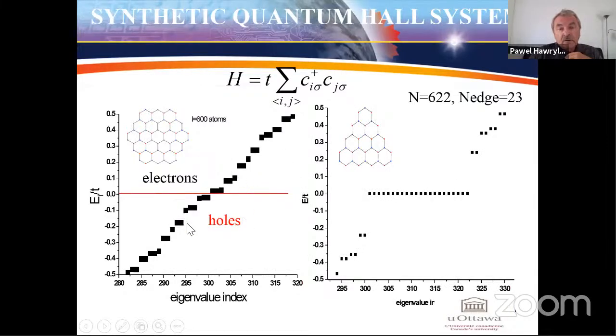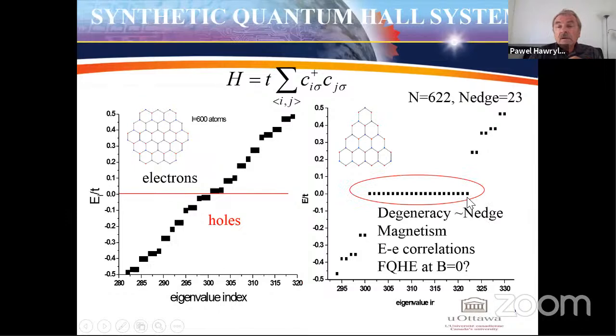Energy levels close to the Fermi level collapse to a degenerate shell. And this degeneracy of the shell is proportional to the number of atoms at the edge. And such a degeneracy implies magnetism, implies electronic correlations, and perhaps fractional quantum Hall effect at zero magnetic field.